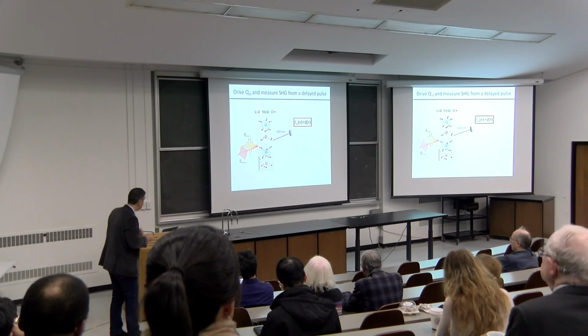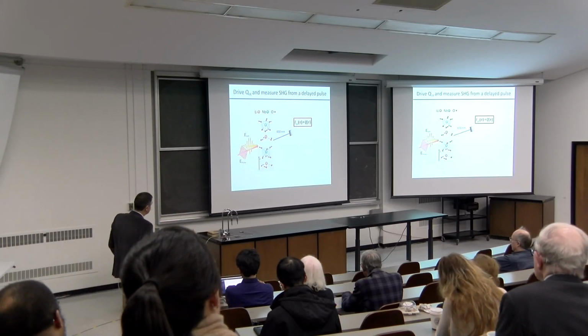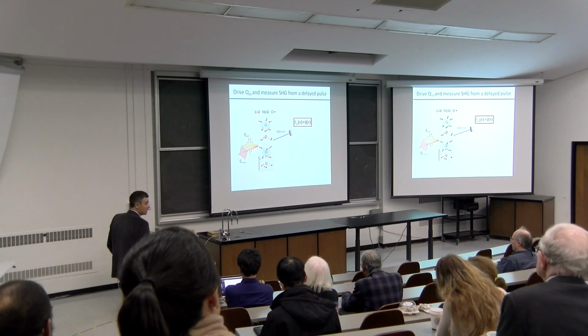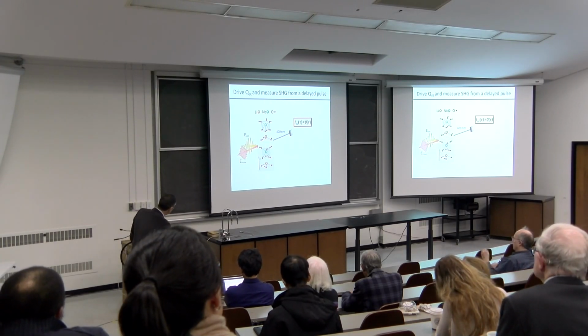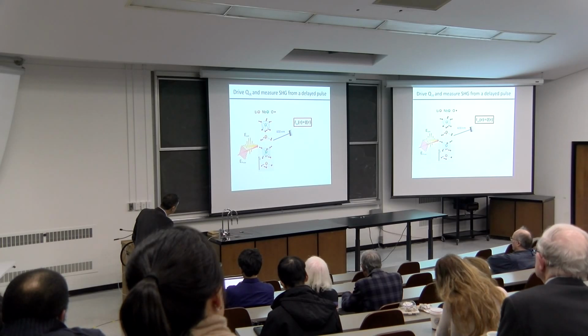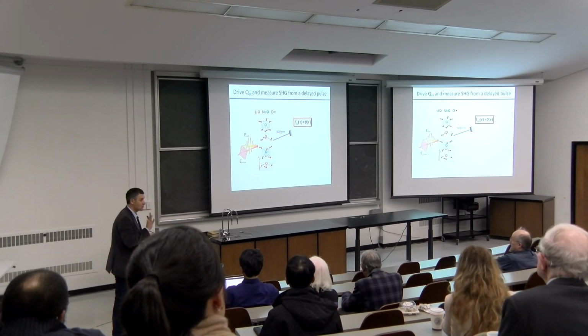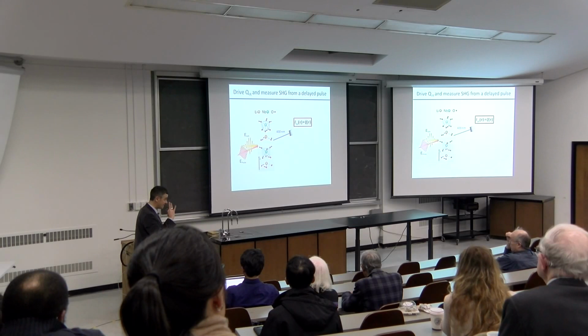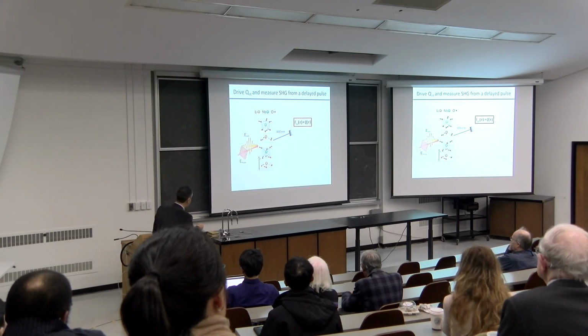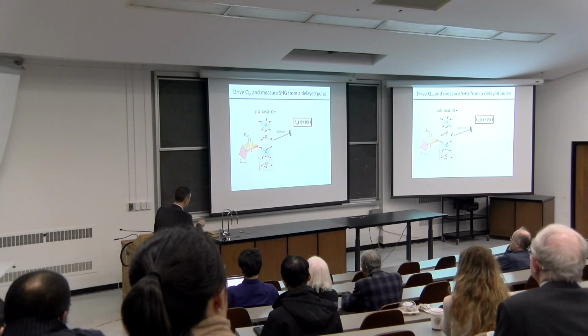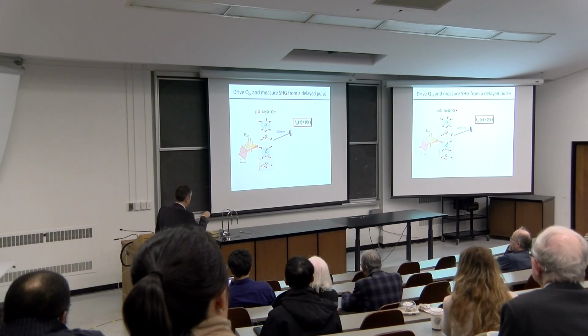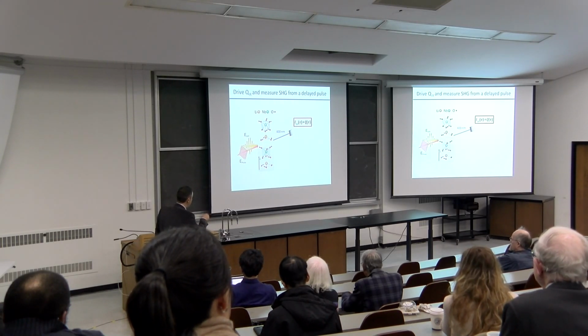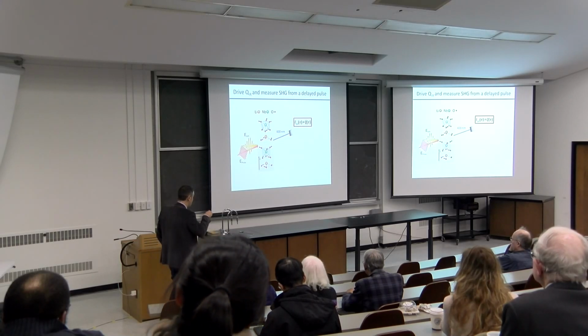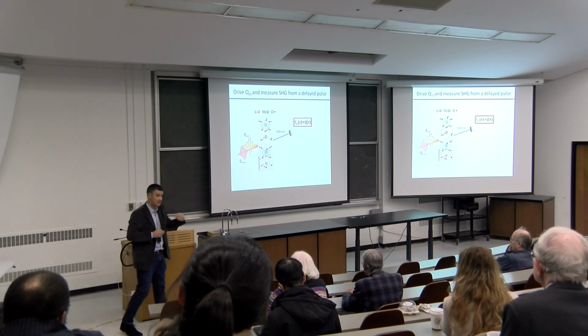So there's a little bit of technique required to do this. And then secondly, I would like to have a probe pulse, for example, an X-ray pulse, which is, however, synchronized with respect to the phase of the first pulse. This is technically not straightforward. I'm going to do the next best thing, which is to use a second visible pulse, which is short enough so that it interrogates the ferroelectric at different times along this pump pulse. Okay? And what I'm going to look at is not the transmission, but the second harmonic generated by the system.